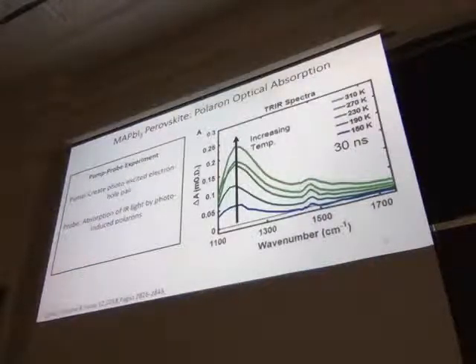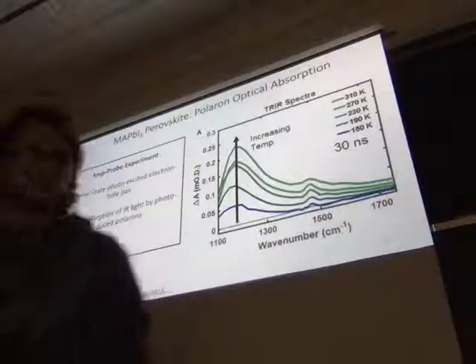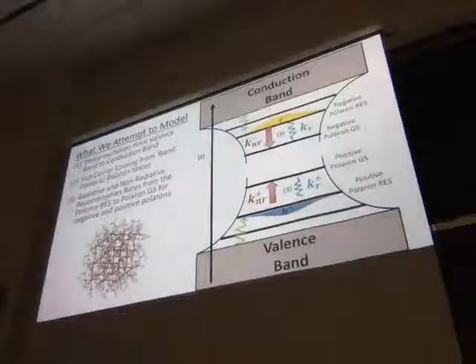And just due to the different chemistry, they see a temperature dependence for polaron absorption. But the results from here indicate that they do see polarons in these materials. And so the next slide outlines, based on everything that we've done over here, what we're trying to model for the dynamics of these systems.